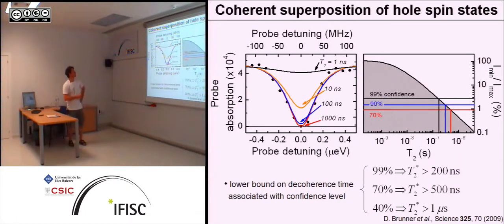Okay, so how do we extract the coherence time of this now? Here are simulations shown with a coherence time of 1 nanosecond. So this is a blow up of this whole optical transition. This is only showing the dark state. So the spectrum will go on and then drop to 0 again, as the normal Lorentzian would be broad like this. And here in the middle we see the dip of the dark state. Now by changing the coherence time of the ground state, this dip gets more and more pronounced. This is just an example, but to really reach the 0 measurement value we got here, we need a coherence time of the ground state of 1 microsecond.